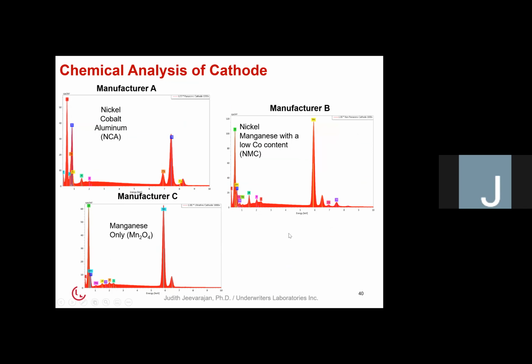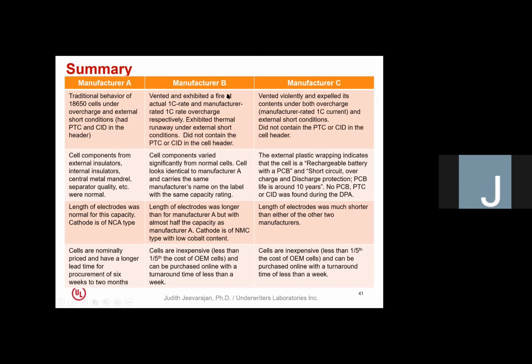We did some chemical analysis and we found that manufacturer A is nickel cobalt aluminum, which is what they tell us it is. Manufacturer B was actually nickel and manganese with a low cobalt content. Probably they were trying to make an NMC. And then with manufacturer C, it was only an Mn2O4 cathode. So this is just summarizing everything. I've mentioned all of that.